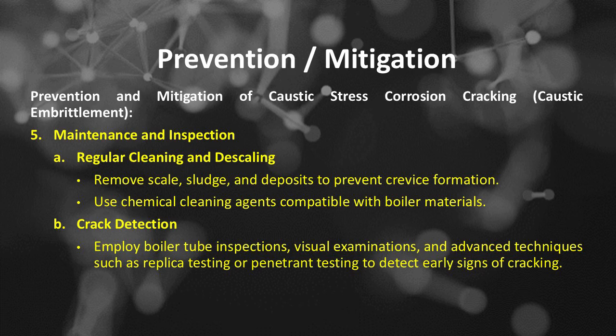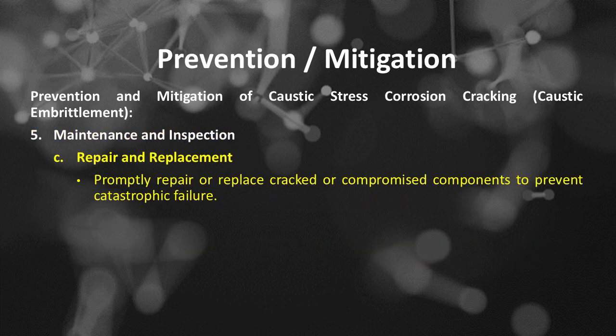Number 5 of prevention and mitigation of caustic stress corrosion cracking or caustic embrittlement is maintenance and inspection, which includes, number A, regular cleaning and descaling. Remove scale, sludge, and deposits to prevent crevice formation, use chemical cleaning agents compatible with boiler materials. Number B, maintenance and inspection for crack detection. Employ boiler tube inspections, visual examinations, and advanced techniques such as replica testing or penetrant testing to detect early signs of cracking. Number C, maintenance and inspection for repair and replacement. Promptly repair or replace cracked or compromised components to prevent catastrophic failure.